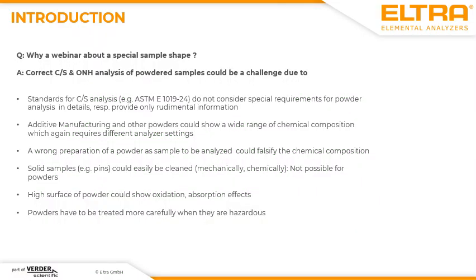One thing which is also important for powdered samples is the step of sample preparation, because when you have a wrong preparation of the sample, it could mean that you falsify the results of ONH and CS in the following. One important thing which is quite often listed in standards is the preparation or the cleaning of prepared samples, which means a solid sample like a pin, for example, is always something which can be cleaned, for example, with acetone or with acids. But when you have to analyze powdered samples, all these cleaning processes cannot be used.